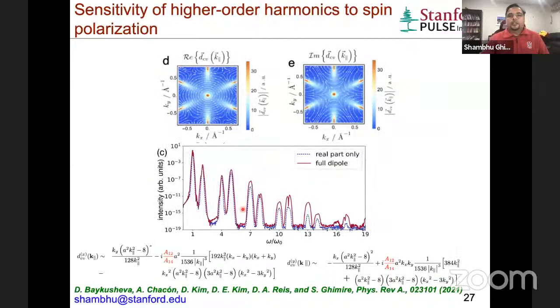This can also be discussed in the context of the interband dipole between these two bands. Here, this is the dipole moment that is plotted, the real part, and this is the imaginary part. And again, because this is a model, you can tweak things and see what affects what. What we find is that the lower order harmonics correspond to this vortex-like feature that is present at the Dirac point. And these high order harmonics are mostly affected by these features that are present at the high momentum places in the Brillouin zone.